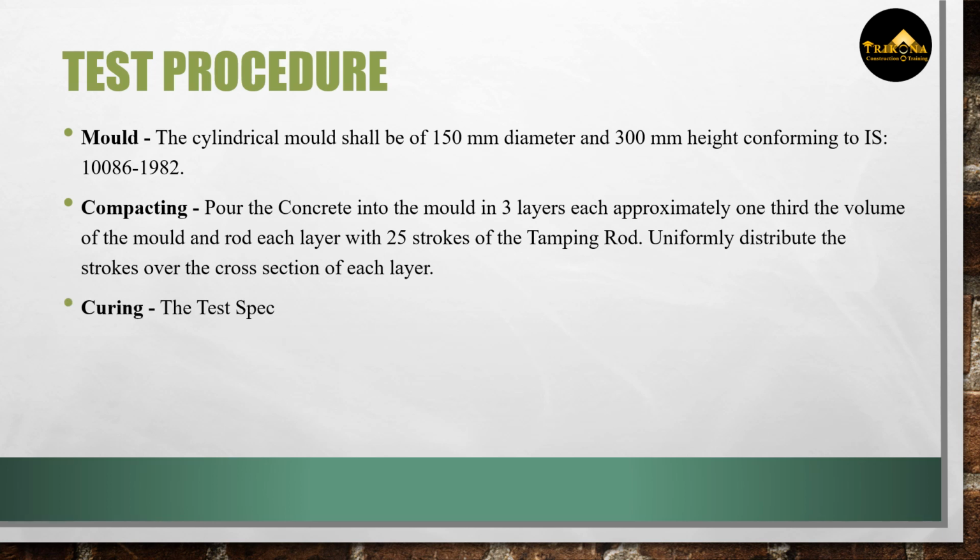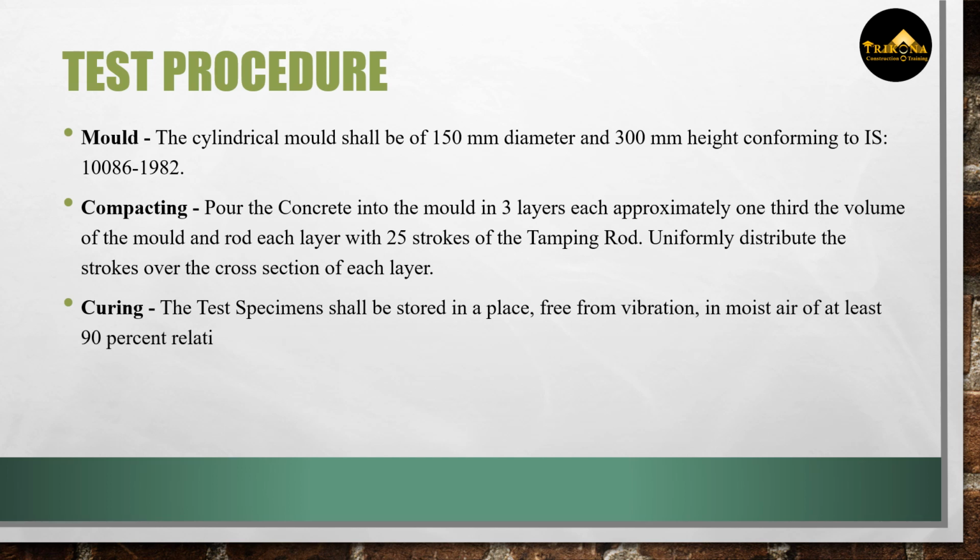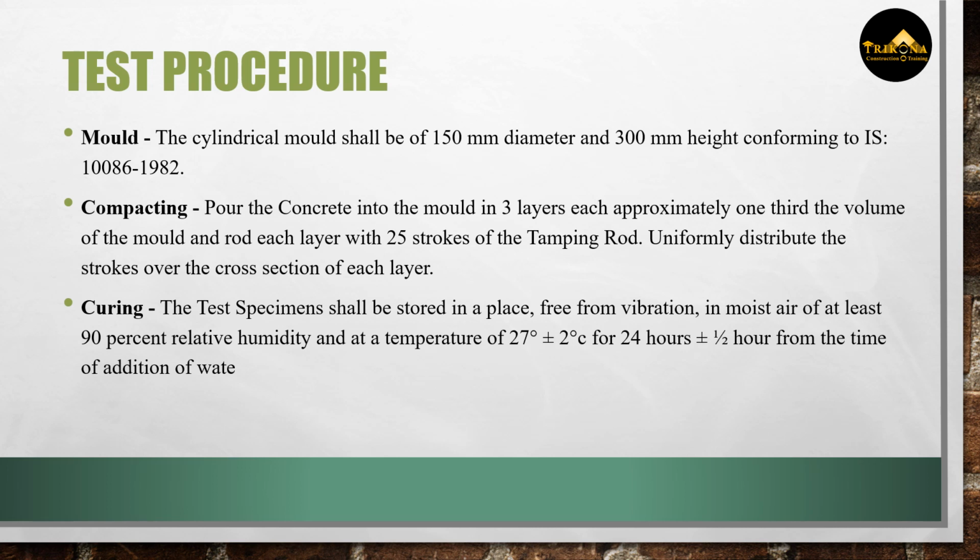Curing. The test specimens shall be stored in a place free from vibration, in moist air of at least 90% relative humidity and at a temperature of 27 degrees plus or minus 2 degrees Celsius for 24 hours plus or minus half an hour from the time of addition of water to the dry ingredients, and then placed in a water tank for 7 and 28 days.